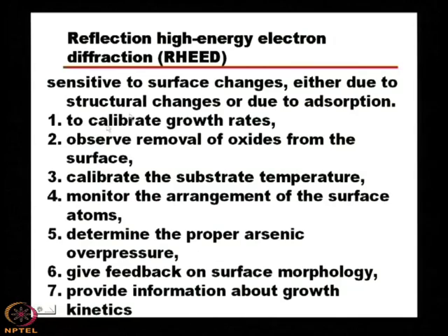Okay. From RHEED, many things you can learn, many things you can understand of the growth. It is sensitive to surface changes, either due to structural changes or due to adsorption. When there is a change in the adsorption pattern, that means the chemical composition will be changed. You can calibrate growth rates. Observe removal of oxides from the surface.